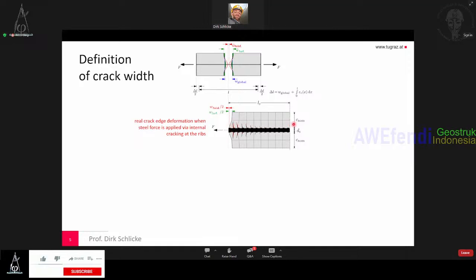And overall, if you make compatibility over the length, over all lengths, this must of course be equal over the height. So if you have a lot of internal cracking near the reinforcement bar, there's of course no real crack opening here at the reinforcement. And if you go away from the reinforcement, you see, well, the internal cracks do not proceed over the entire concrete cover. Of course not, because this gets weak due to the small crack, then strain gets a bit smaller. This is already somewhat stiffer, and the crack growth into the concrete gets smaller. And if you look at the primary crack, you see, well, if there is no internal crack at the surface region, of course, there's also no crack opening. The crack opening of the primary crack must increase. Otherwise, you would not fulfill compatibility.